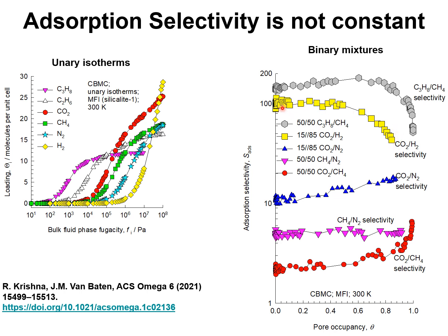At pore occupancies below about 0.5, the adsorption selectivity is strongly in favor of CO2. The adsorption selectivity is about 100, but decreases to about 40 at high pore occupancies, because hydrogen, the smaller molecule, is able to occupy the vacant spaces in the pore landscape more easily than the slightly bulkier CO2.